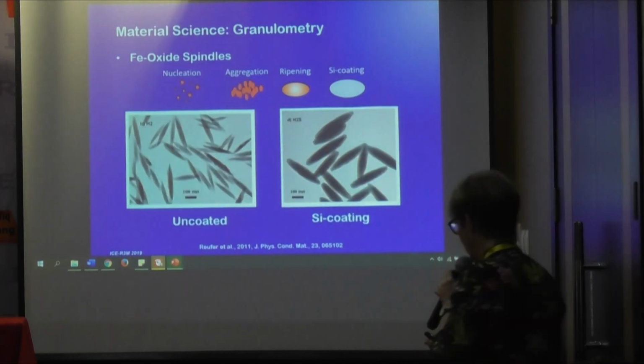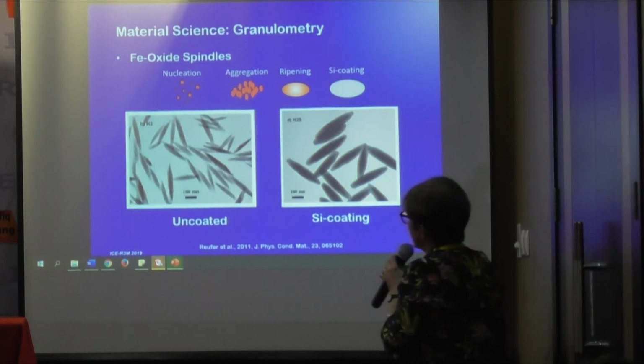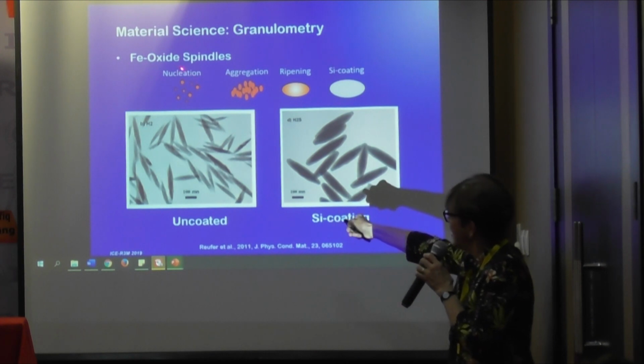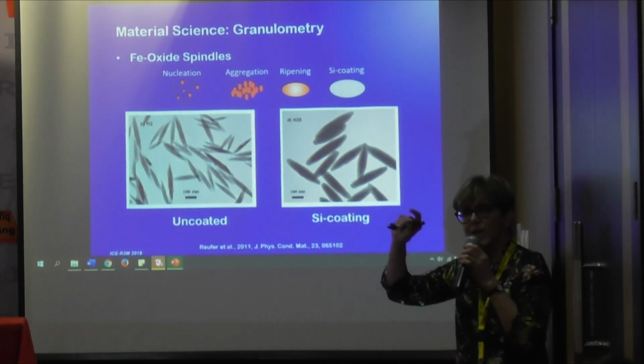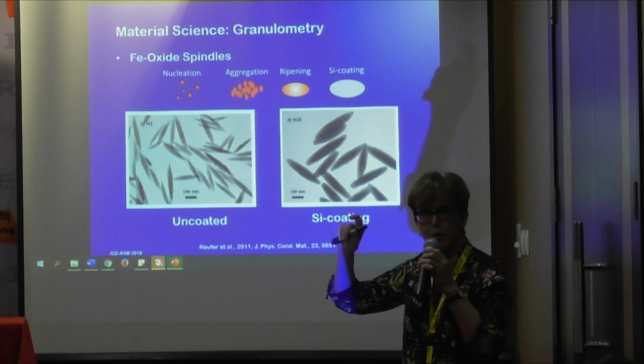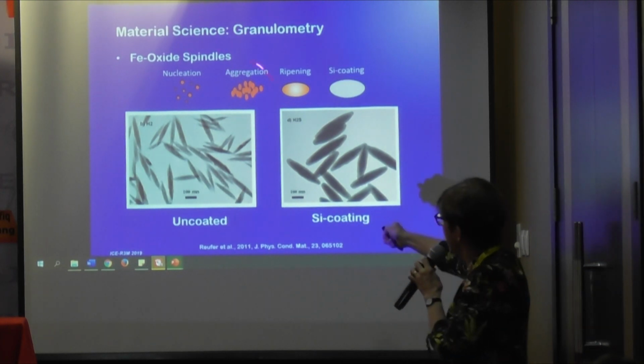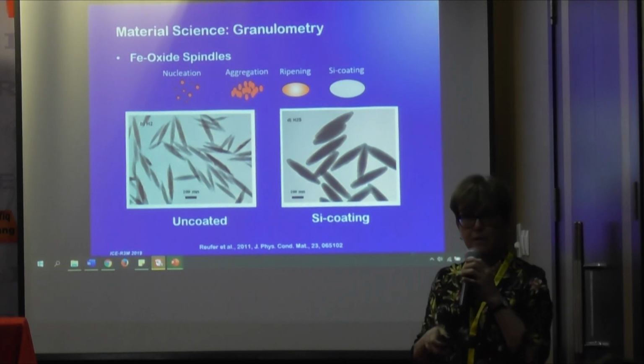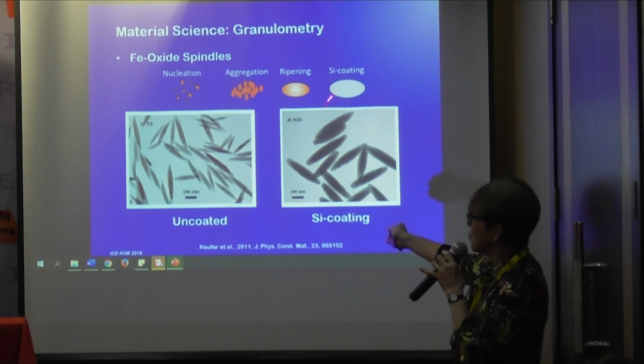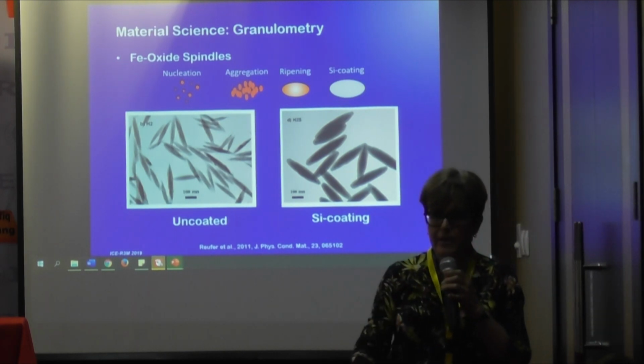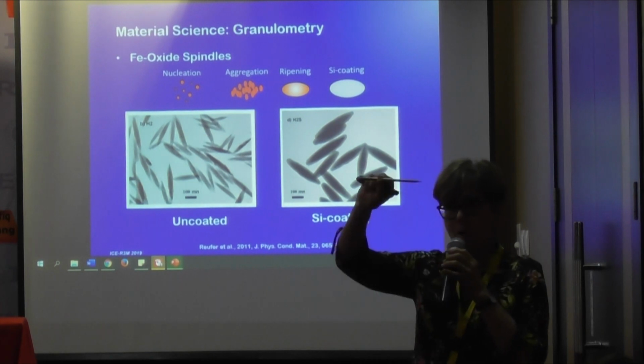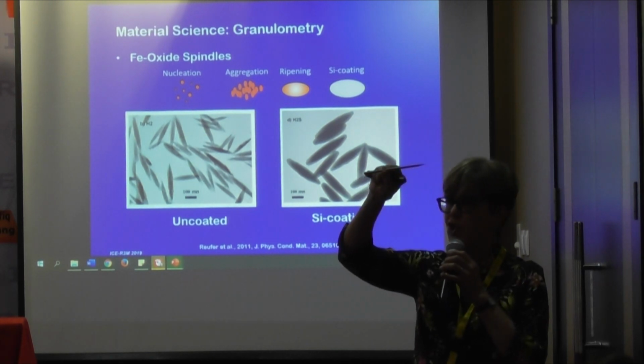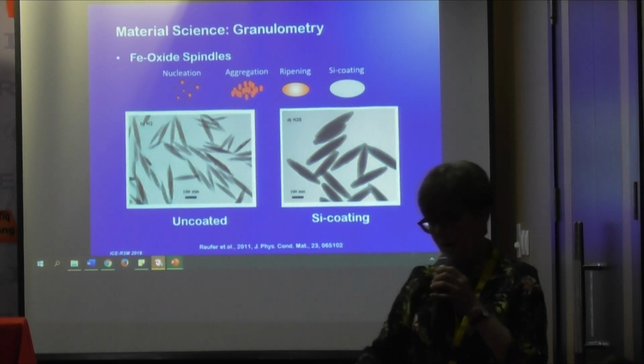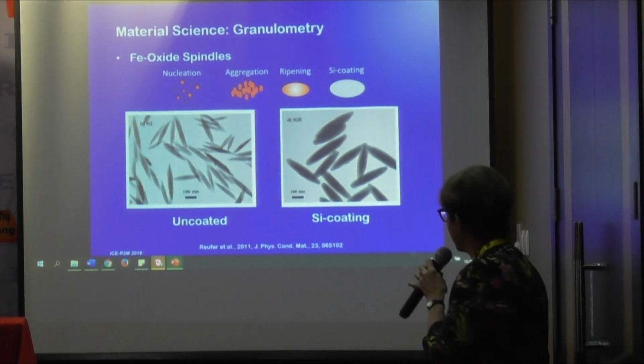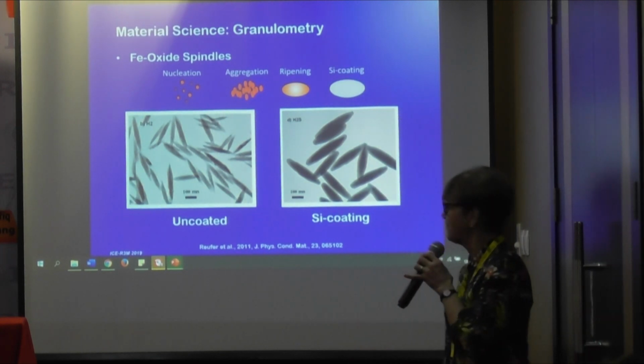Okay, next. So if you go back to how they make these particles, they start out with very fine particles on the order of 5 nanometers, and then these 5 nanometer particles aggregate together, and then they undergo something called ripening. So their idea is those aggregates of particles all come together and form one big giant hematite crystal. But in reality, that's not what happened.